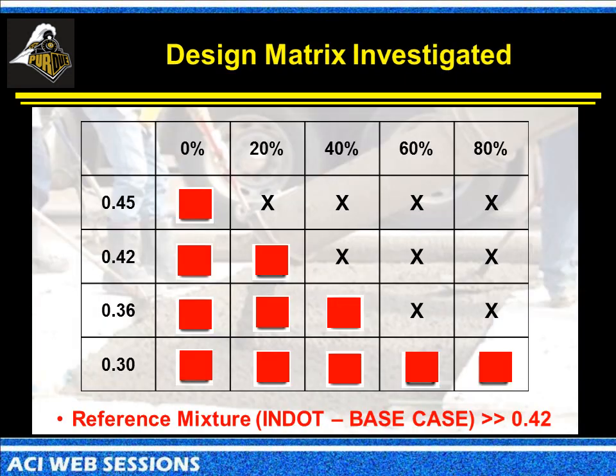The matrix that we're looking at in this project is anywhere from 0 to 80% volume replacement with the fly ash, with water cement ratios from 0.45 all the way down to 0.3. This is the baseline that we will typically be going back to and comparing against.